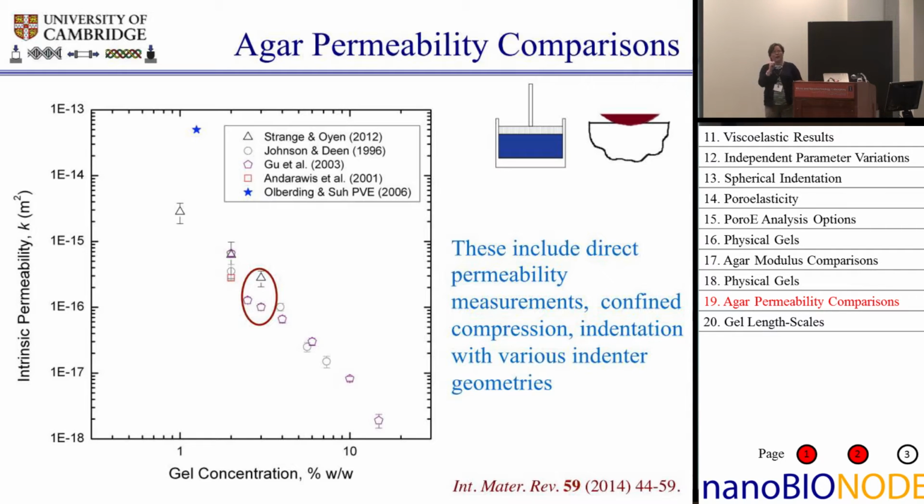The interesting thing about this is that because the agar relaxes so much, it can't physically be purely poroelastic. In order to achieve that total amount of deformation and not have a negative Poisson's ratio, you would have to have some viscoelasticity in the solid skeleton. And you can actually calculate how much that should be from basic principles. If that's something you're interested in, I'd be happy to talk about that with you at the break.